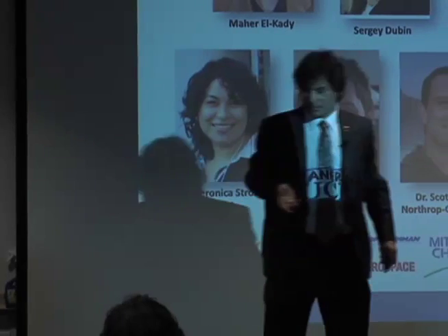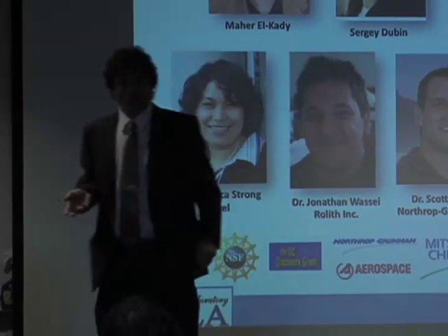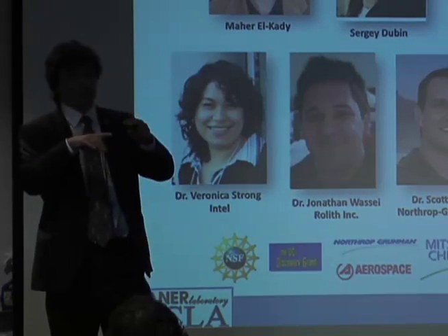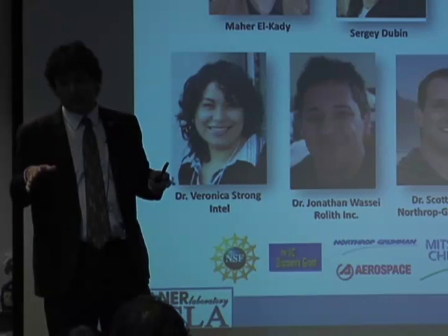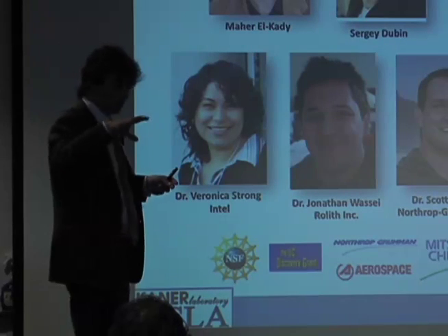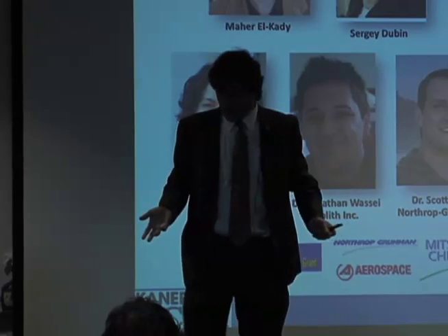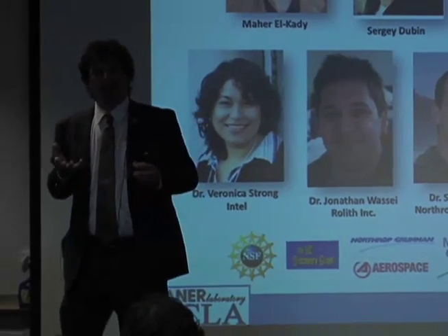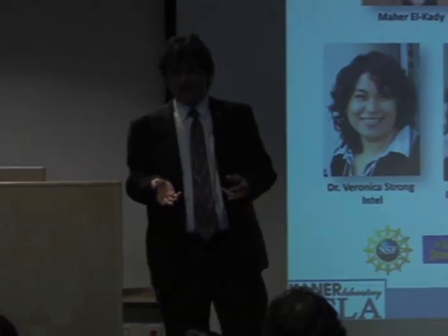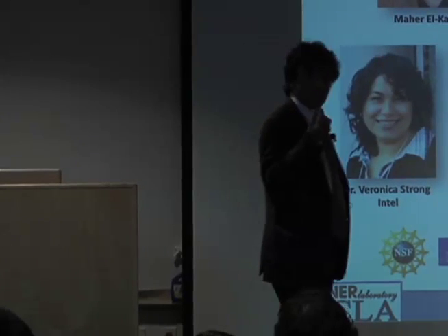And I had this conversation at lunch. You can talk to people who do supercapacitors, and you can say, supercapacitors have a little bit of degradation. They can go millions of cycles, but they lose a little bit of capacitance. If you're in the battery industry, you look at them and you're like, wow, that's amazing. But then you can ask, why do they degrade? And they degrade because of impurities. It can be oxygen impurities, it can be metal impurities in the carbon.